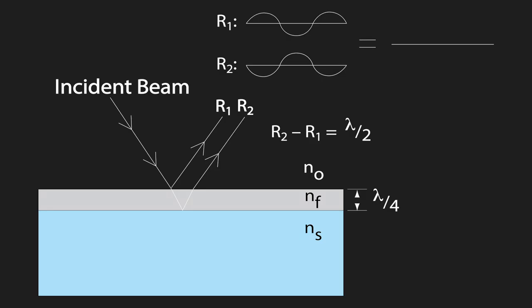Optical coatings are composed of a number of thin film layers that create an interference effect used to enhance transmission or reflection properties within an optical system. The performance of a coating is determined by the number of layers, the thickness of each individual layer, and the different refractive indices of the layers.